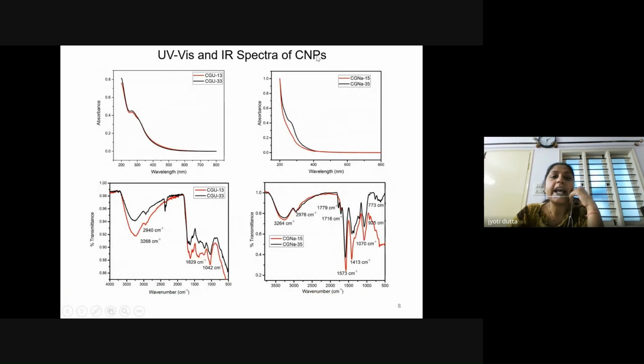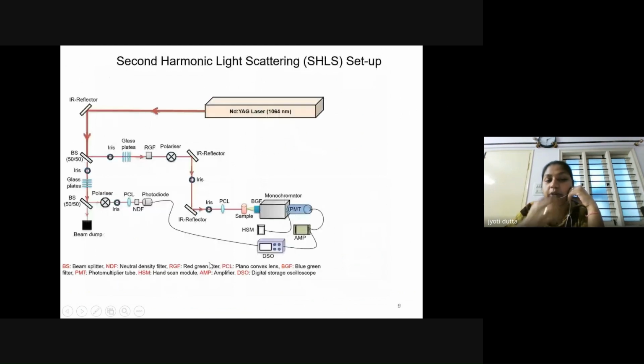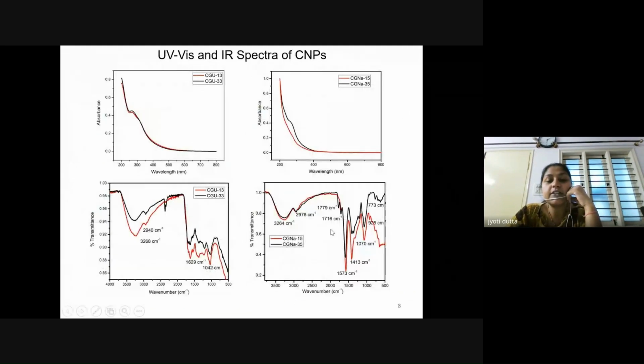Now we checked the UV visible and IR spectra of these CNPs. Here are the UV spectrum and the IR spectrum. The carbonaceous nanoparticles made from glucose and urea had major peaks of OH stretching and CH stretching, as well as a peak at 1629 centimeter inverse for the C double bond O carbonyl group. And in the second set of carbonaceous nanoparticles, made from glucose and sodium hydroxide, we observed other functional groups. For example, we can see 3264 centimeter inverse for OH stretching, then CH stretching at 2976 centimeter inverse. There is also carbonyl stretching at 1779 centimeter inverse and 1716 centimeter inverse, which can be because of the presence of carboxylic groups.